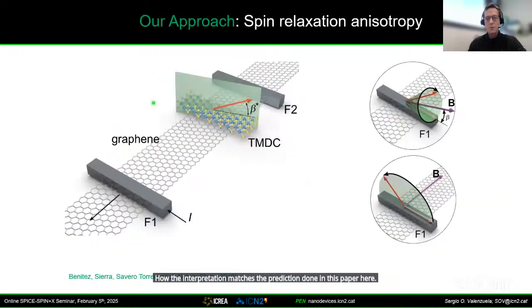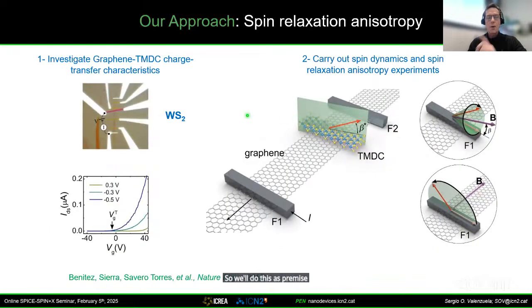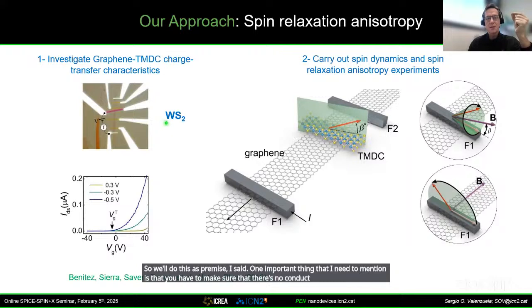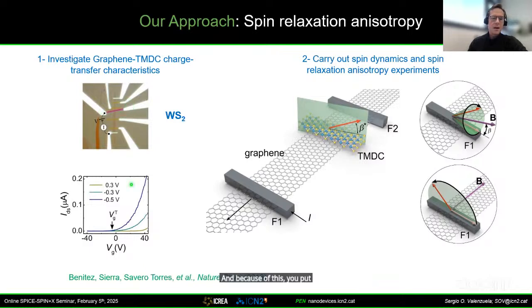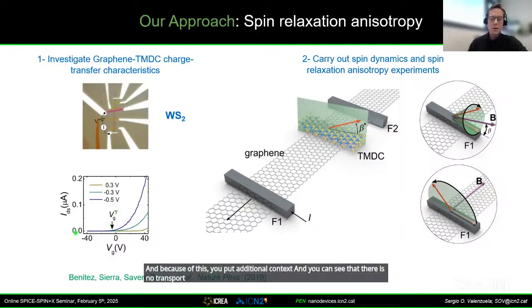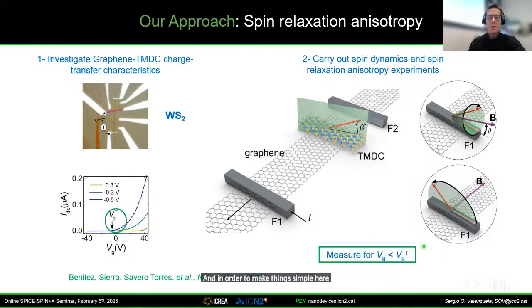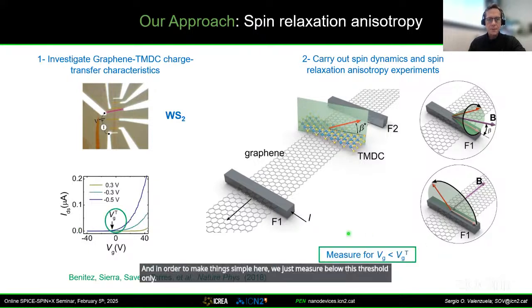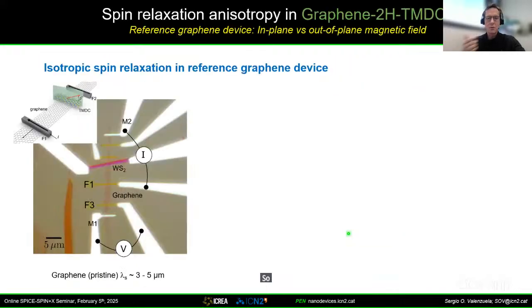So we'll do these experiments, I said. One important thing that I need to mention is that you have to make sure that there's no conductivity in the transition metal dichalcogenide, or you can control it and investigate it. And because of this, you put additional contacts here, and you can see that there is no transport below a certain threshold. And in order to make things simple here, we just measure below this threshold only. So it's all proximitized. There is no contribution from the transition metal dichalcogenide.